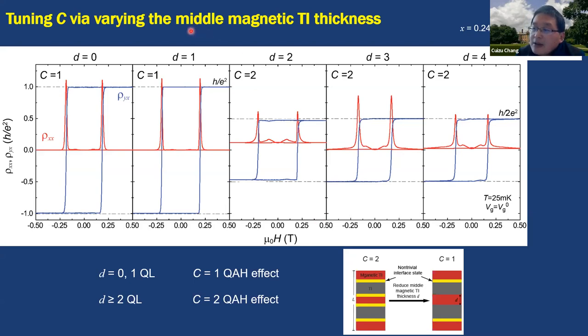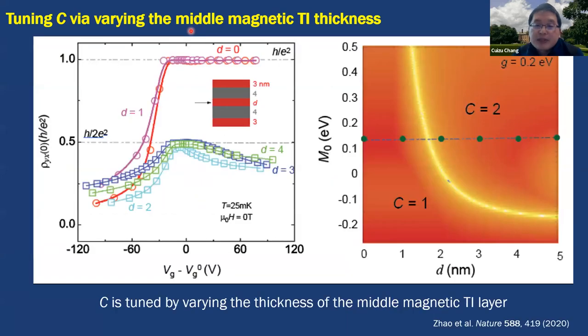This change of the thickness of the middle magnetic TI layer is further demonstrated by the gate dependence of the zero magnetic field Hall resistance. We can see that when D equals 0 and D equals 1, it is indeed quantized at h over e squared Hall resistance. For D from 2 quintuple layers to 3 and 4 quintuple layers, at the charge neutral point, the Hall resistance is quantized at h over 2e squared. This experimental observation is also well interpreted by our theoretical calculation. If you tune the thickness in the middle, you can change the C equals 1 quantum anomalous Hall insulator layer to the C equals 2 quantum anomalous Hall insulator layers.